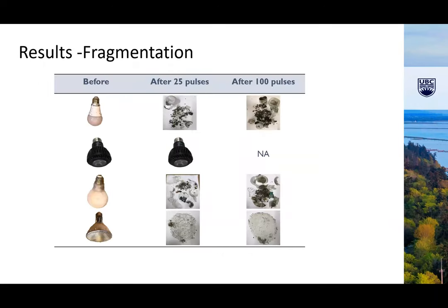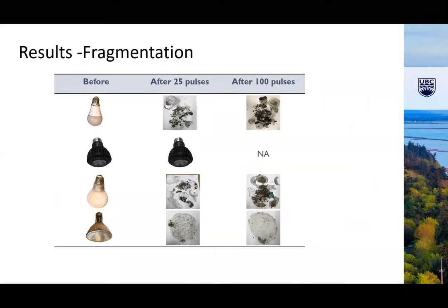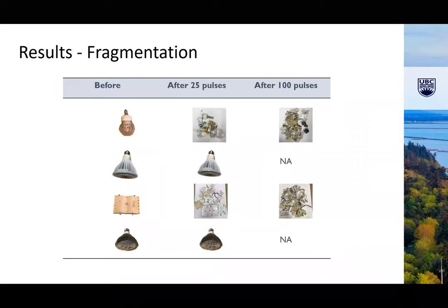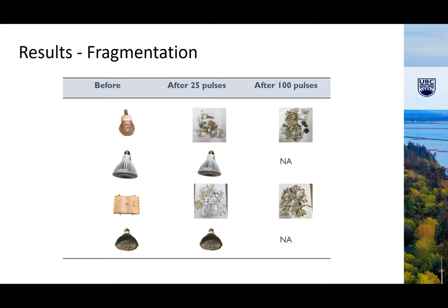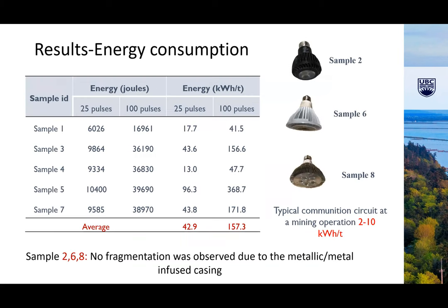When we look at the fragmentation, several of the lamps did not perform well. As you could see, they were not disintegrated. As I mentioned at the beginning, one of the characteristics of LED lamps is that they're very strong against breakage, and that's shown to be the case, definitely for some designs more than others. And here are another 4 lamps, where 2 of them did not follow the trend of being disintegrated.